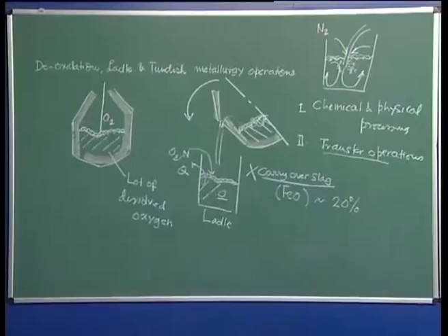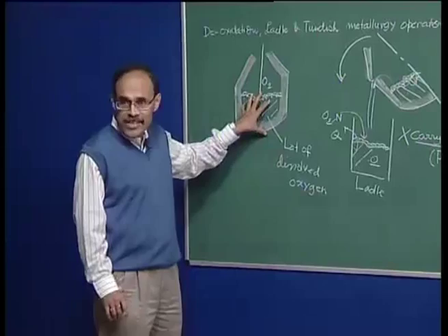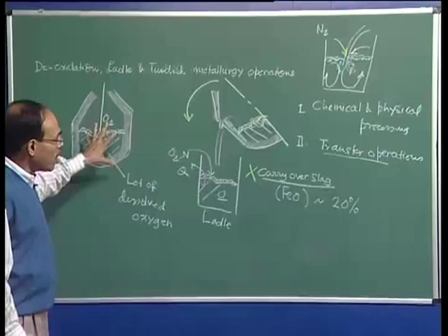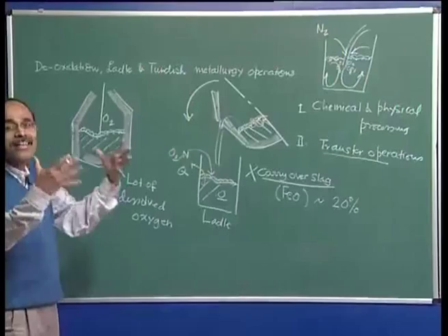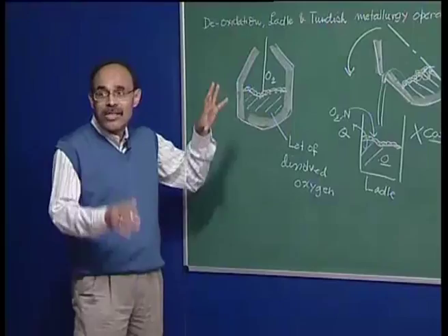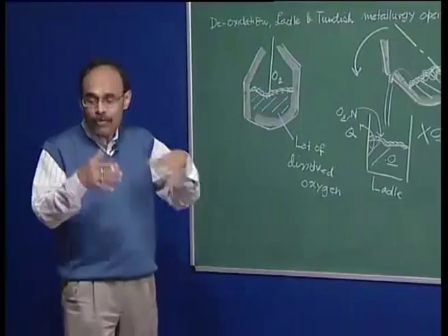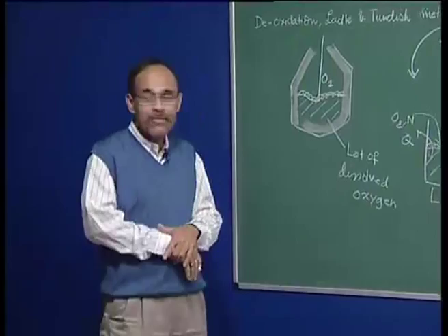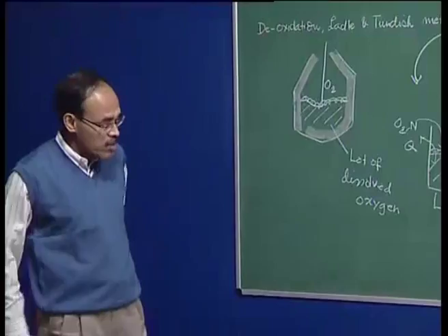So, refining is far from being complete in the primary steel making vessel, and that is why there is a need for many subsequent operations, or an entire ladle metallurgy treatment station, in steel plants to adjust the composition and temperature of steel. And I repeatedly say temperature and composition. Composition is to meet the demand of the customer, and temperature because there is a stringent requirement on the part of continuous casting that the metal be delivered into the continuous casting mold at the